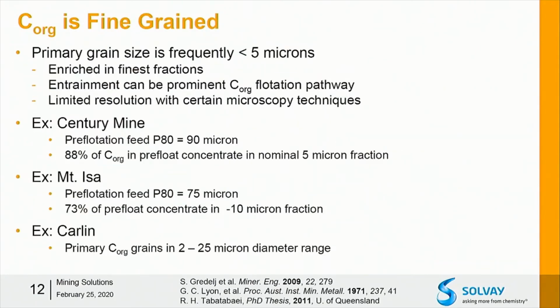Okay, so in addition to that, carbon tends to be very, very fine-grained. Primary particle size of carbon is typically less than 5 microns. A good example is Century Mine, again, P80 of 90 microns in the pre-flotation circuit. 88% of the carbon in the pre-float concentrate was in the 5 micron fraction. And this is really seen consistently across a range of different sites. It's very rare to see any sort of coarse-sized carbon, and if you do, it's probably not liberated.